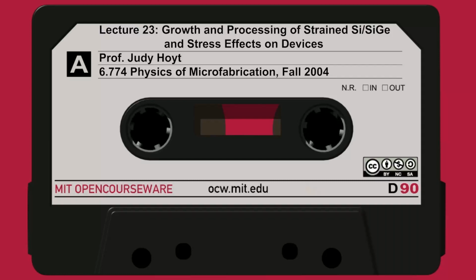Silicon germanium carbon is in production now, maybe not silicon carbon, but silicon germanium carbon, with very small amounts of carbon, maybe 0.5%, as a way of suppressing transient enhanced diffusion in heterojunction bipolar transistors. So I think somebody's doing a report on that. One of the people signed up for that. So that's kind of a hot topic, the use of carbon to completely suck up all the interstitials, and that completely changes the TED effect. So these materials have quite a bit of application.